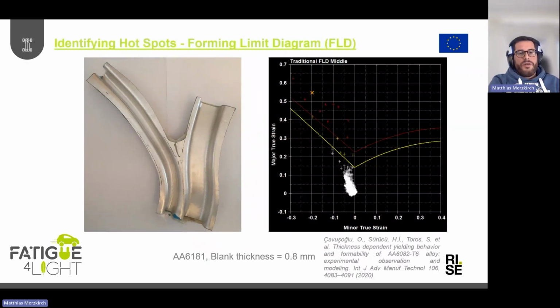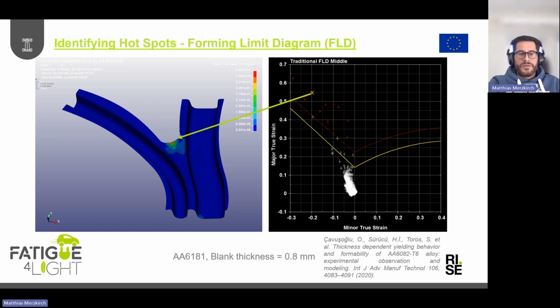In that case, a forming limit diagram was used. So in order to compare that also to the predictions, because as you might know, in order to get those numbers for forming limit diagram, you have to do a lot of testing, very complex testing, but based also on literature values and the similarity between the 6181 aluminum and the 6082 aluminum alloy, it is at some point also a little bit understandable how and why it broke. So we actually see here that we have the highest strain in this region, well, in that case also predicted the cracking, and this could also be simulated. So these are the values here.